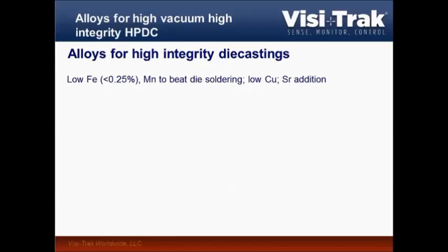They all need relatively low copper. How low should be determined in the salt spray test. And they all have strontium additions at different levels for different purposes. Typically, strontium is added only to modify the eutectic silicon. In the case of the Mercalloys, it's also used to beat die soldering.